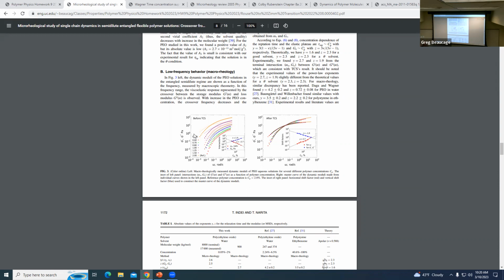The other one's like a cone and plate viscometer where they're doing oscillatory, so oscillating it. The third one is DWS, diffusive wave spectroscopy. So it's a dynamic light scattering. You put beads of known size into the stuff. Then from the mean square displacement of the beads, you can figure out the viscosity of the fluid, believe it or not. And you can get the G prime, G double prime as a function of frequency from it. So it's basically the magic method.